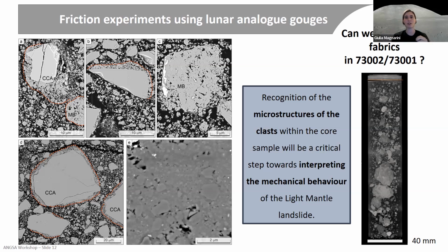So in a landslide context, that would correspond to a zone very close to the basal surface, whereas the core sample represents the top 60 centimeters of the landslide deposit, which is estimated to be at least several meters thick. So in a way, it probably doesn't even represent the entire landslide deposit. Plus, the sample may not yield pristine structures anymore.